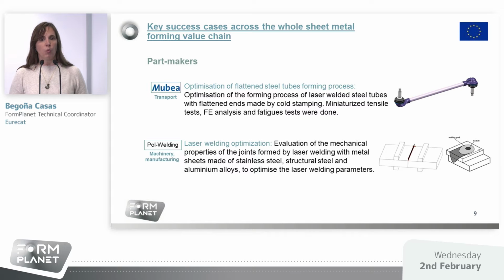In the case of Pol-Welding, we performed an optimization of laser welding. We evaluated the mechanical properties of the joints formed by laser welding of metal sheets made of stainless steel, structural steel, and aluminum alloys to optimize the laser welding parameters.